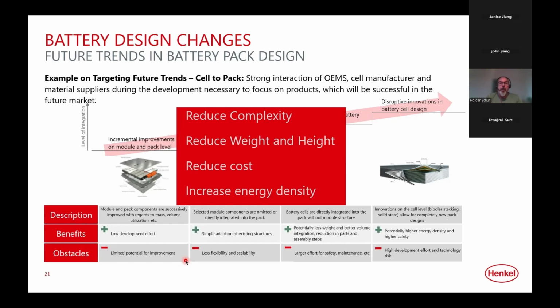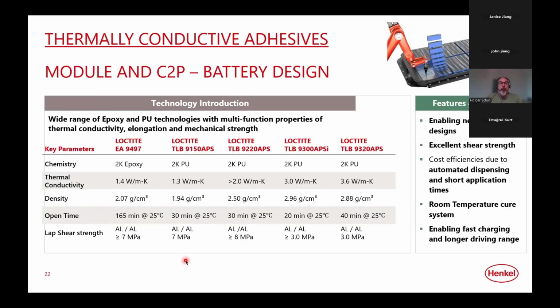And for that reason, there's a strong move away from the gap filler, which are not that mechanically robust. So they are not bonding at a high level. And that's where we see a trend that people are asking for what we call the thermal conductive adhesive. So that's the module bonding or the cell to pack approach. And also here we have different types of material, either epoxy based or polyurethane based, with different thermal conductivity grades from 1.3 roughly to 3.6, also with different density, everything driven again to room temperature cure. And as you can see here, also with different lap shear or mechanical characteristic. So that's the portfolio we have today.